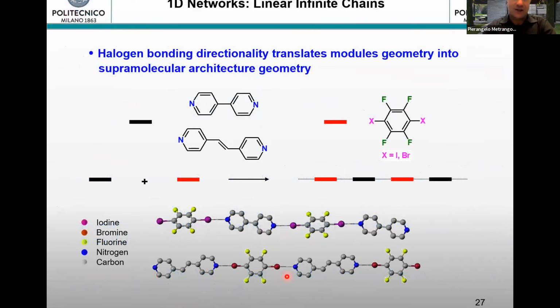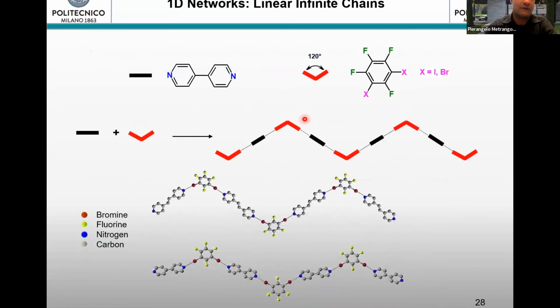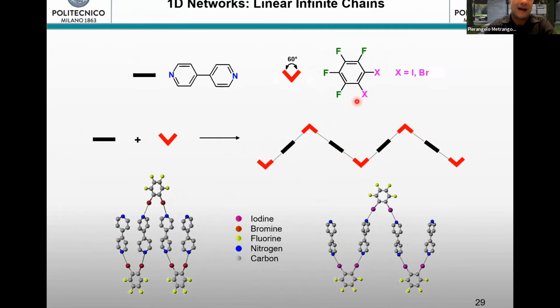So the directionality is very high, which means that you can plan your co-crystals, making, for example, linear chains, or if the halogen bond donor moieties are at 120 degrees, then you make zigzags, or even narrower zigzags if the two halogen atoms are at 60 degrees.